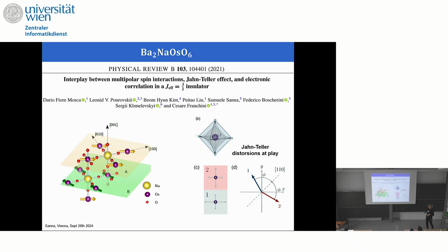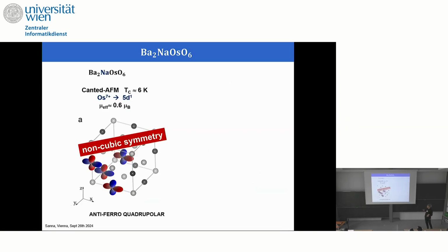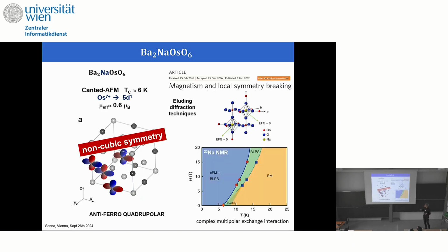Everything has been already well described, from the theoretical and the experimental point of view. I would like to say that we are almost convinced, I think everybody here during these days was convinced, that the system in the sodium is mainly non-cubic. We should also remind again, maybe after 100 times in this conference, that the first experimental observation that the system could be distorted, at least locally, was from Ba2NaOsO6 in 2017.